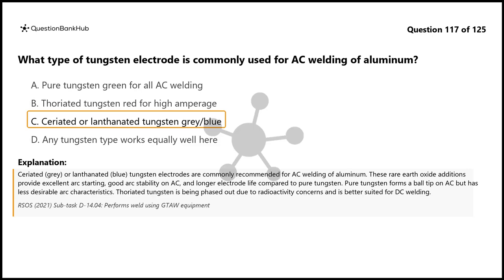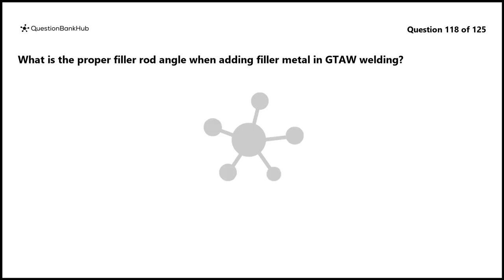These rare earth oxide additions provide excellent arc starting, good arc stability on AC, and longer electrode life compared to pure tungsten. Pure tungsten forms a ball tip on AC but has less desirable arc characteristics. Thoriated tungsten is being phased out due to radioactivity concerns and is better suited for DC welding. Question 118. What is the proper filler rod angle when adding filler metal in GTAW welding?